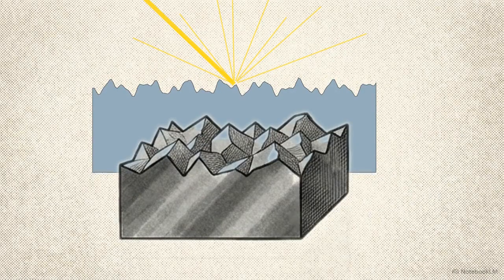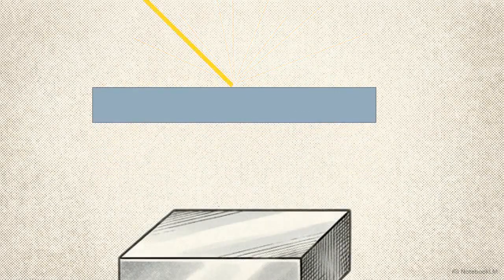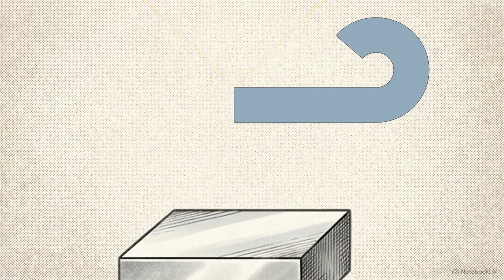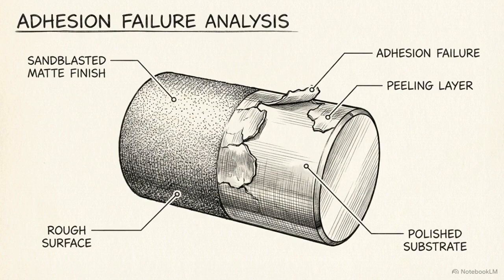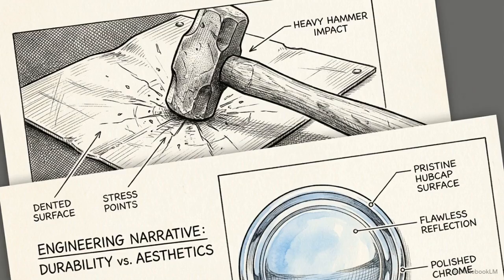This engineering conflict is the adhesion-gloss paradox. Making the substrate rough enough to hold the coating securely causes incoming light to scatter. But smoothing that jagged substrate to reflect light perfectly erases physical anchor points. The coating loses grip, delaminates, and peels off. Relying entirely on traditional mechanical methods to prepare the metal forces a compromise. You can have physical durability, or you can have a pristine, highly reflective surface, but you cannot achieve both.